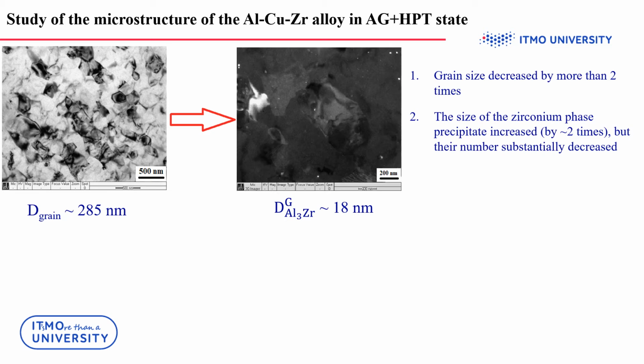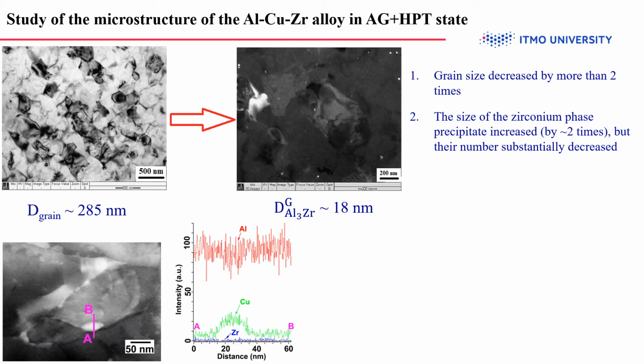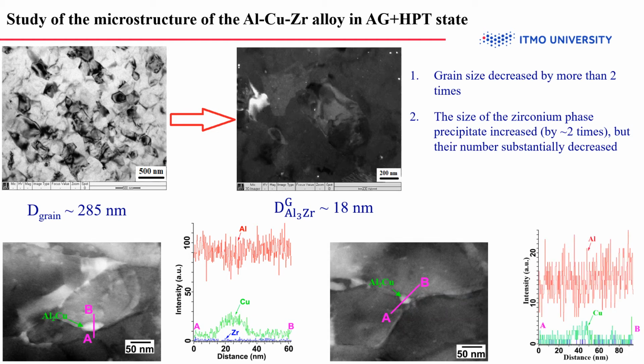The number of aluminum-zirconium precipitates substantially decreased, however, the average size increased to 18 nanometers. The precipitates of aluminum-zirconium are predominantly located in the grain interior. That pointed to partial deformation-induced dissolution of these precipitates. At the grain boundaries, copper-containing precipitates, the aluminum-copper phase with an average size of 20-40 nanometers, are clearly observed. Their belonging to the copper phase was confirmed by microdiffraction images and EDX analysis in STEM.